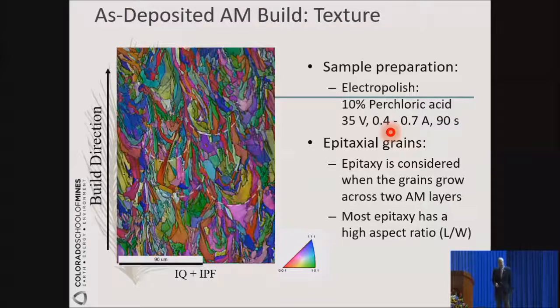So now you look at the AM texture, using electron backscatter diffraction, and epitaxy is there. But epitaxy in these cases, in 304, doesn't go through multiple layers as in the titanium case. In this case, most of them will be going through maybe a couple of layers. And you can see the white lines here showing you the bottom of the deposit. And then you see that there are grains that, see here, go through about 2 layers. That's about the average that we have seen. Okay, so another one on this side here.